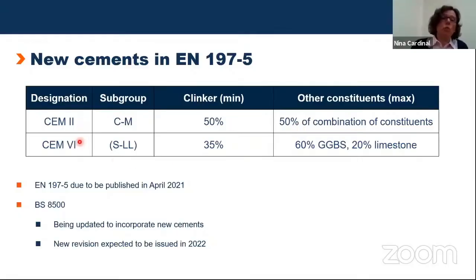And there will also be a new group of cements, the CEM6 group, and it will have 4 different subgroups, including slag limestone and fly ash limestone cements. I've just given here one example. So in the CEM6 group, the minimum clinker content is down to 35%, and you can use in combination up to 60% GGBS or 20% limestone to replace clinker.